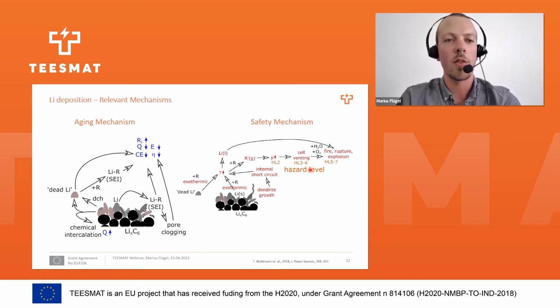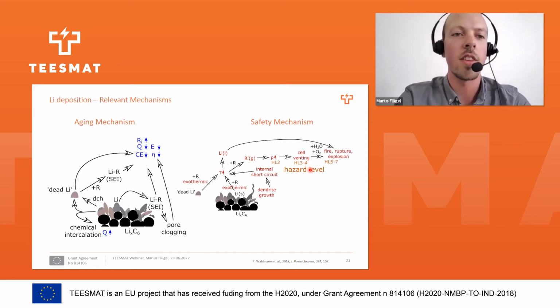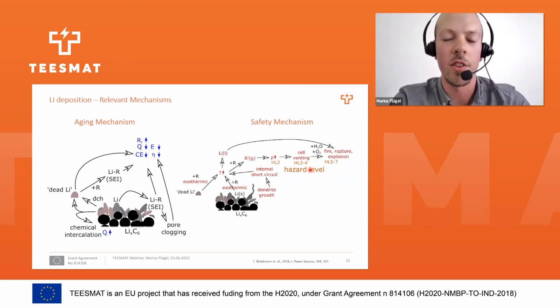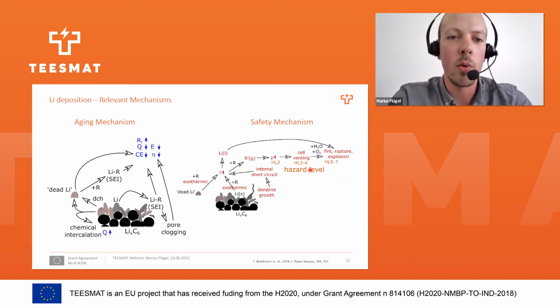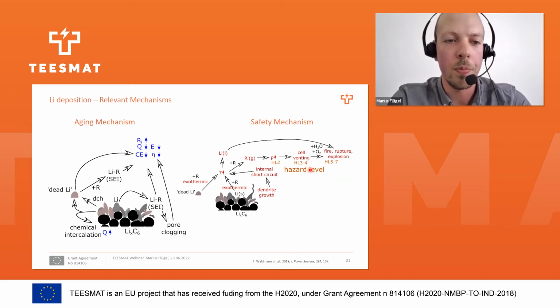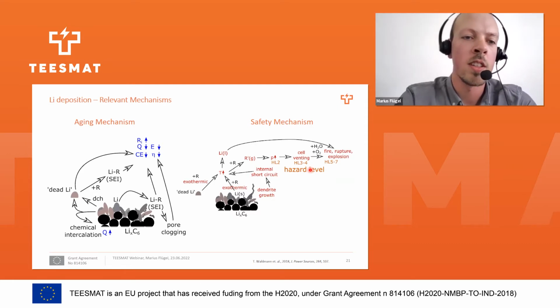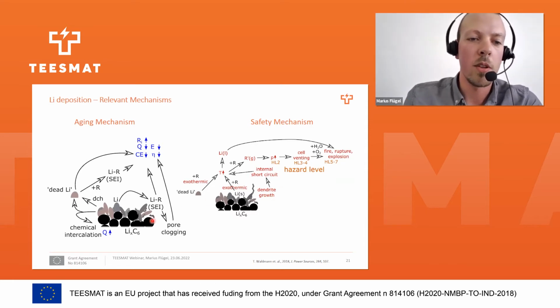Our main focus with GD-OES is on the detection of the lithium deposition on anodes. This is very relevant as lithium plating on top of the anode poses a serious threat to the electrode. It's possible for the lithium to reintercalate into the anode or to dissolve during discharge.